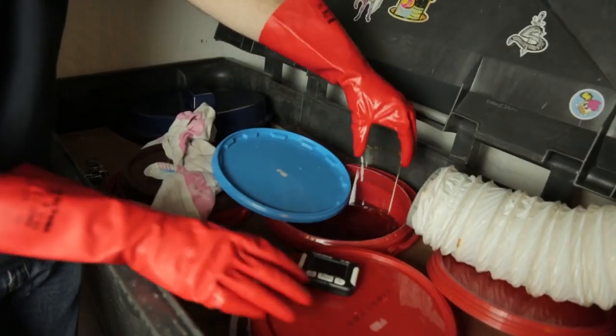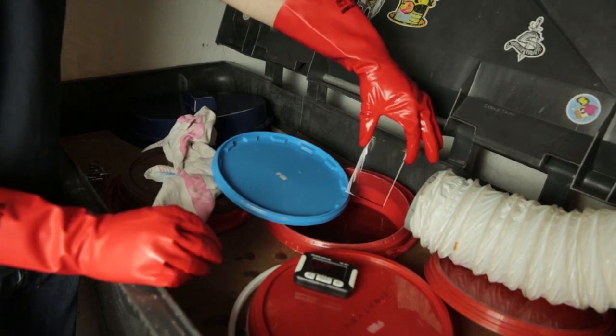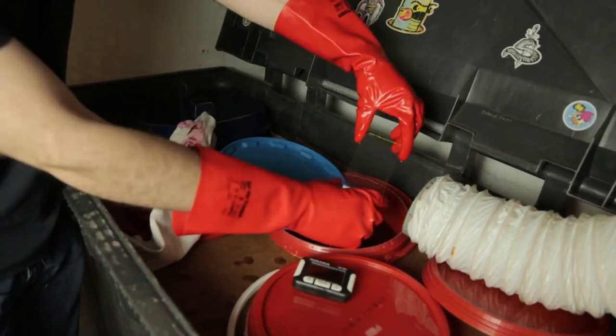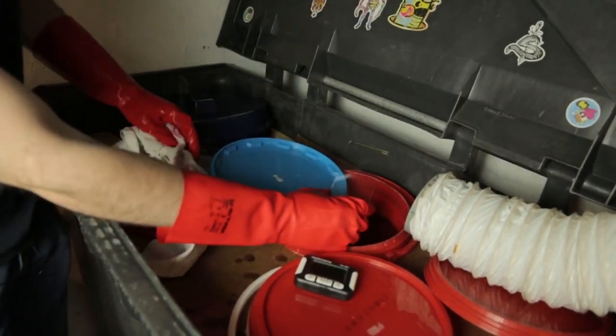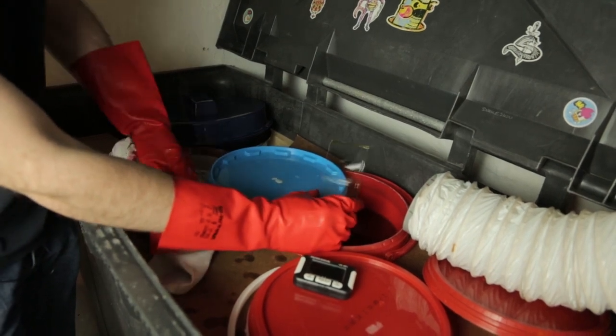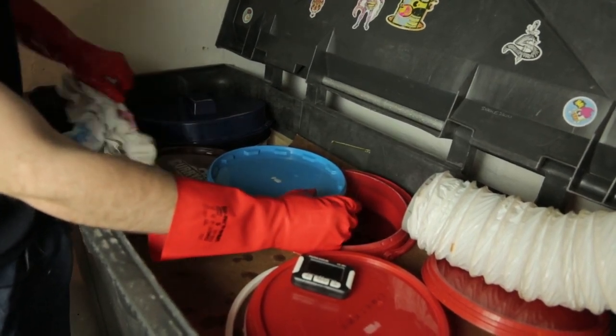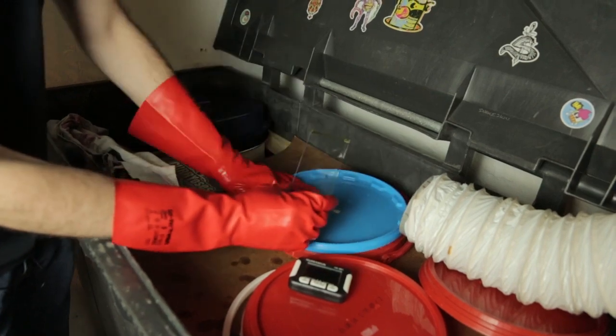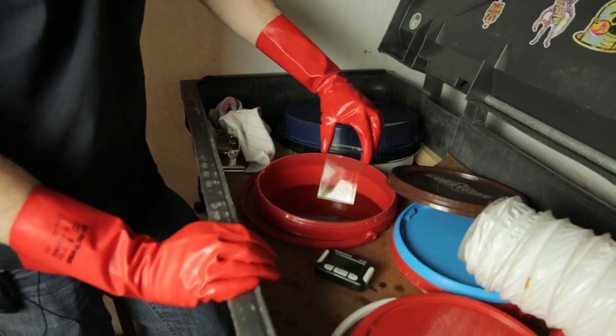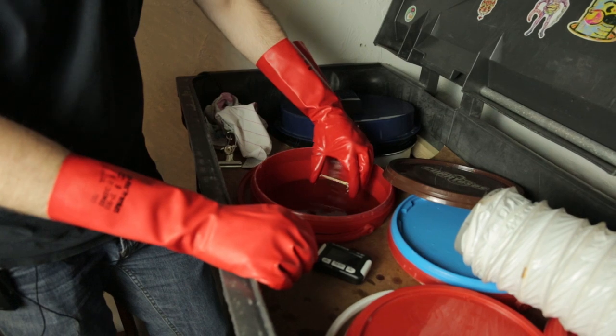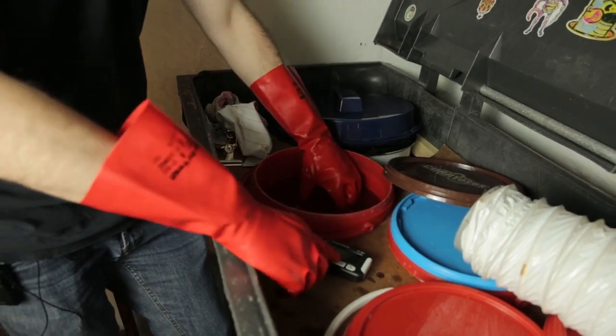Inside the tank, the emulsion will turn from gooey to solid. Coming out of the 59%, the gelatin will have become rigid. It's now closer to being a solid than a liquid. When I take the plate out, I watch for the snake skin. Once I see it, I slowly immerse the plate into the 84% bath, where it will remain another 25 seconds.